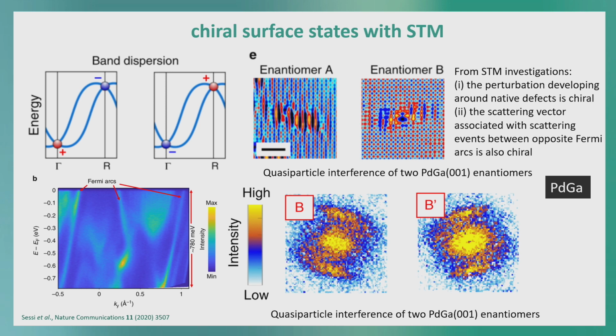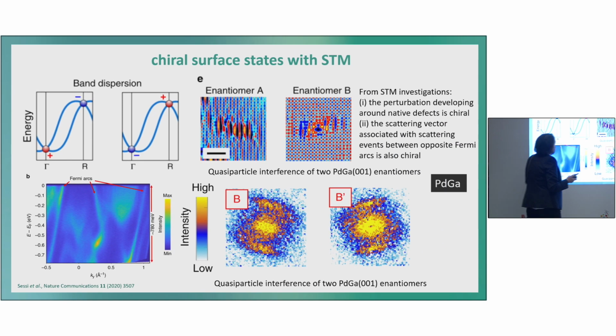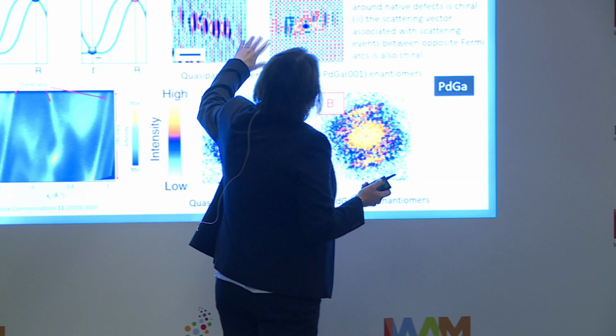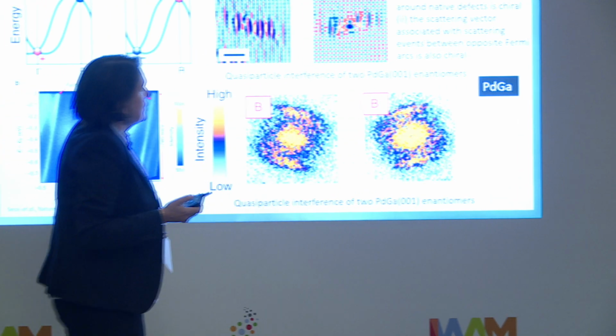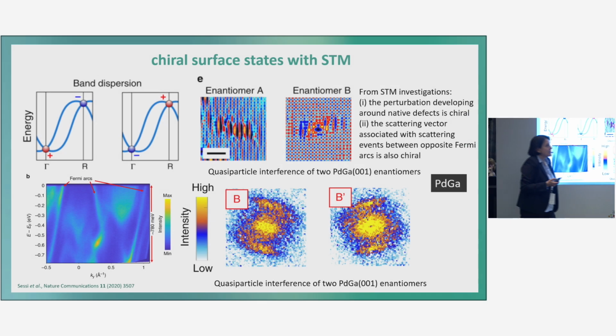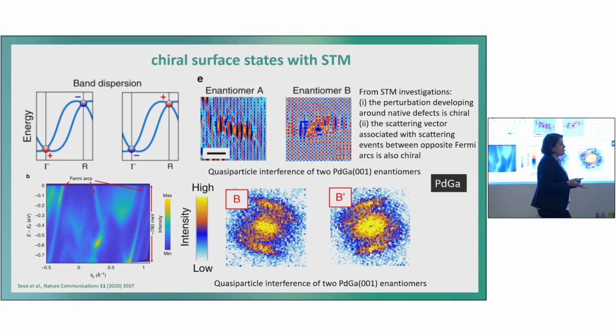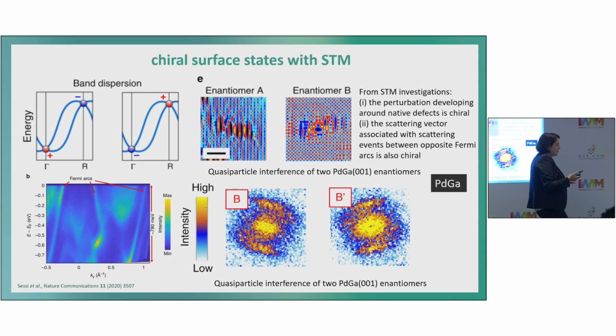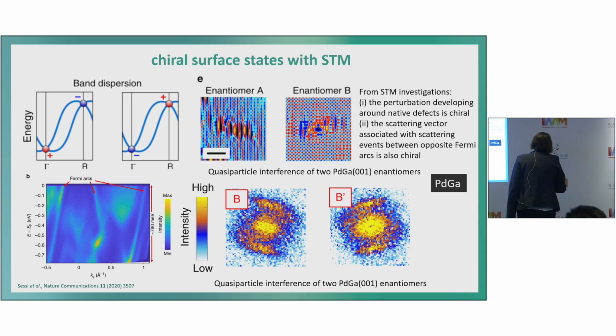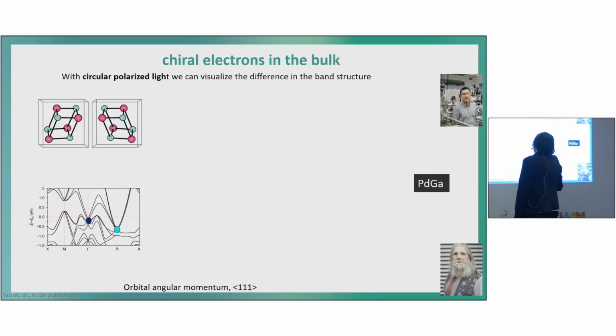This is interesting if you go to a defect, and this makes a connection to why I'm quite excited about catalysis. If you go to the defect, and this is nice work in collaboration with Stuart's group, you see already in the scattering vectors and so on, if you have both different chiralities of the crystal, that the defects are in some sense chiral. I thought maybe there should be a chance at the end of the day to do something with these materials.